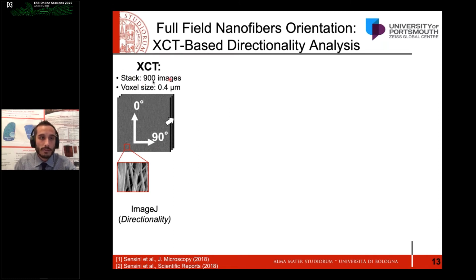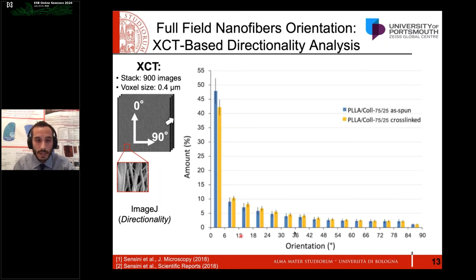Taking the different stacks of the XCTs that we obtain from our different bundles, and deciding to place at 0 degrees the axial orientation and at 90 degrees the circumferential orientation of the nanofibers, we investigate each slice of each stack of our bundles, then calculate the mean and standard deviation for the different ranges of angles of each scan. What we obtain are histograms like this, where the x-axis shows the orientation, the different degrees of orientation, and the y-axis shows the percentage of nanofibers aligned at those different degrees.